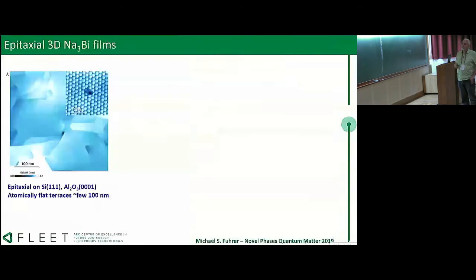Okay, so we can grow nice films. This is STM of a thick film on silicon 111. You can see terraces that are over a couple hundred nanometers. You can resolve the sodium atoms on the surface. This is a missing sodium atom vacancy, which we do see. We can grow them also on alumina, which is insulating, so we can do transport measurements.